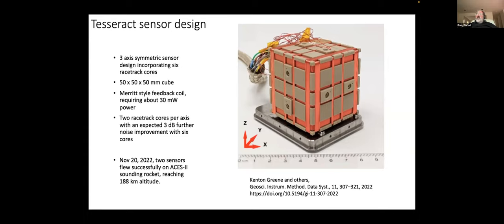And as a result, there is that 3 dB improvement that you can expect from using 2 instead of 1. So when I said there was a typical five picotesla per root hertz in the previous slide, by the time you get to using 2 cores, you're down to 3.5 picotesla. For me, I can't measure that. My lab's too noisy now to be able to see that. And Dave's struggling to be able to prove that he gets that kind of numbers. Environmental contamination makes these kind of tests quite hard to do.